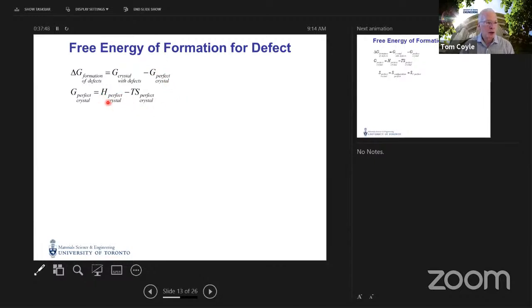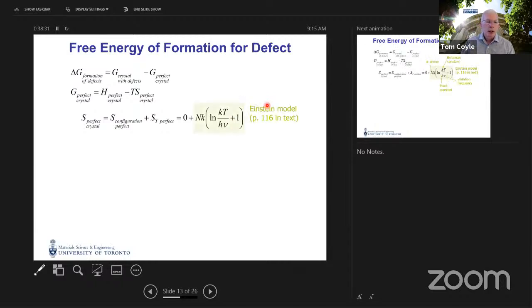And so we can break that down into enthalpy and entropy contributions, where the entropy change is that between the perfect crystal and that of the crystal containing a defect. So the entropy of the perfect crystal is made up of the defect configuration. There aren't any defects, so that in the perfect crystal is 0. And then the statistical part of the entropy. This statistical part, we can make use of the Einstein model to describe the factors that contribute to that.